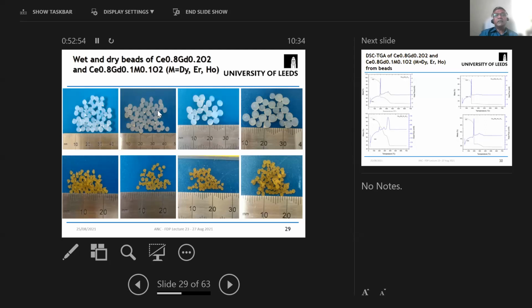At the top are the wet beads after ion exchanging. So these are oven dried. They're not yet transformed into nanoparticles. But you can see that there is about 50% shrinkage. These are about 4 millimeter in diameter here, whereas down here, the dried beads are about 2 to 2.5 millimeter in diameter. So there's about 40 to 50% shrinkage in the beads. So you can imagine that 40 to 50% is the water content in these beads.